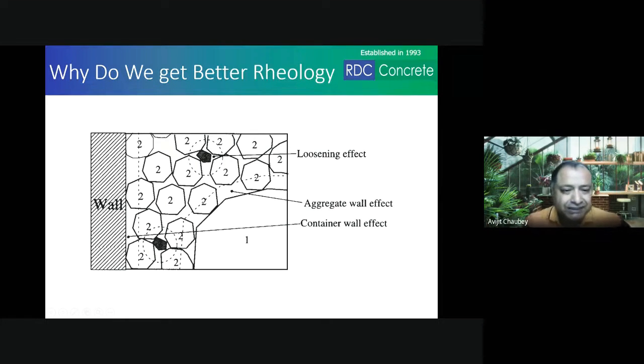This wall effect is not necessarily closer to the cube surface, the cube wall, or the structure, the form work. It can be true even against the bigger aggregate size. So wall effect is, let us say, if the aggregate was not here, there could have been another, smaller aggregate that could have come over here. Since this aggregate has come here, this point is with void. This point is with void because this wall has come, and this aggregate is not able to fit in this small space, so it pushes away. And this is called the wall effect. This happens near bigger size aggregates, and also near the structure, the form work.